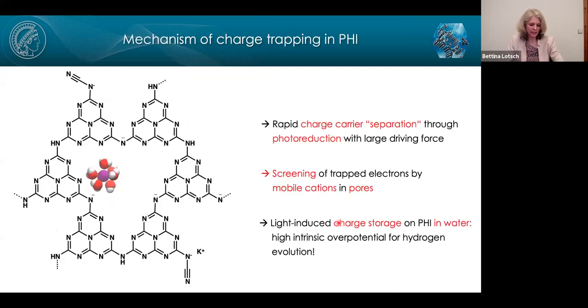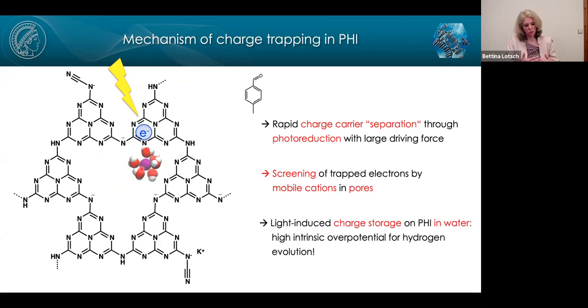So basically, the question is, why is the system so special and different from other types of carbon nitrides? What we see is a very rapid charge carrier separation after excitation and formation of an exciton. So we rapidly extract the hole by a sacrificial electron donor. That leaves us with the trapped electron on the system. But the trapping is assisted by mobile alkali metal ions in the pores that can move up to the electrons. That's the picture we have in mind, and really screen the electronic charge on the carbon nitride backbone.